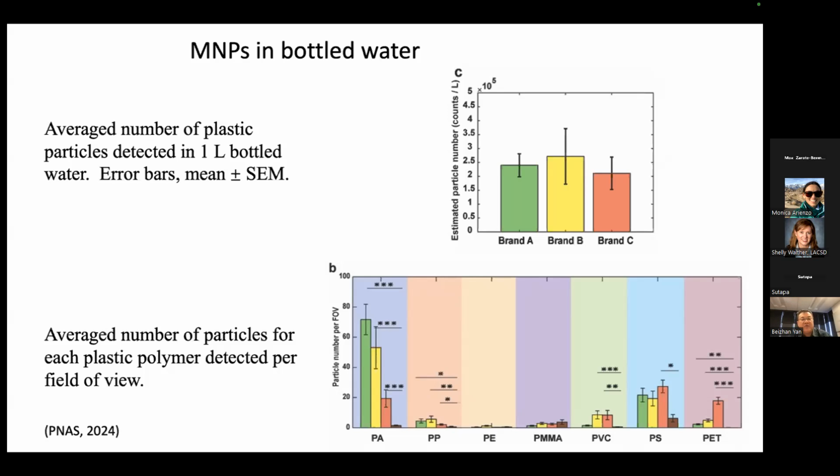When we started writing this paper, we realized that reverse osmosis actually uses polyamide, PVC, and polystyrene. They are the materials that make the reverse osmosis. So ironically, it can remove the particles from the source water, but it is also shedding particles into the water that is made. Of course, this is still our assumption.